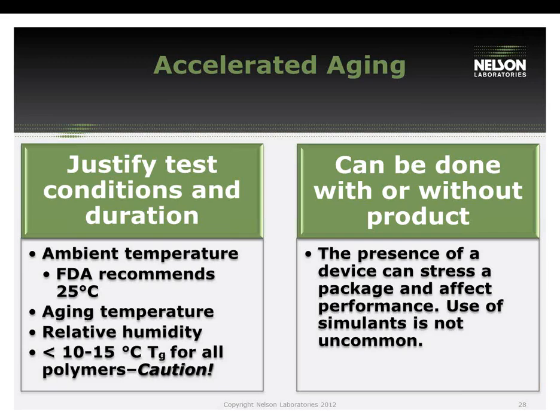Additionally, you want to make sure that your Tg, which is your thermal glass transition point for polymers, is at least 10 to 15 degrees below that value. What happens if you approach it is once you put your samples into the aging chamber, they come out all melted, and that's not good for anybody.